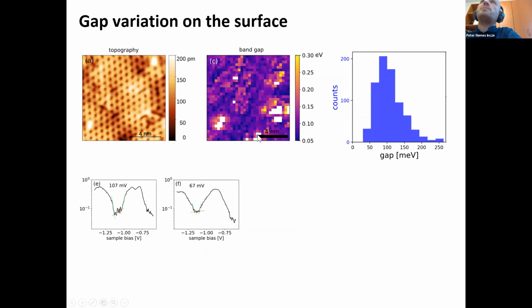So here you can see a map of the band gap on this area shown on the left image. And you can see in this histogram that most of the band gap values are around 100 millivolts, but you get much larger values as well. So I think that this 100, 110 millivolts for the band gap is possibly a lower estimate because defect states that can show up in your band gap can reduce the size of this in the STM measurements.